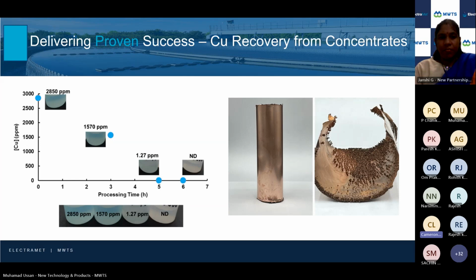So look at these lines here coming in from the feeder at about 3,000 ppm. So this is the effluent from an electrowinning reactor. So it takes the copper from whatever 10,000 plus ppm down to 3,000 very efficiently and produces the copper too. We then use our mid-range delta system to take it from 3,000 ppm down to anywhere below 500. And this one we kept going, it's very linear. So that means you have the same efficiency down to about 1 ppm. And in this case, that met discharge compliance.